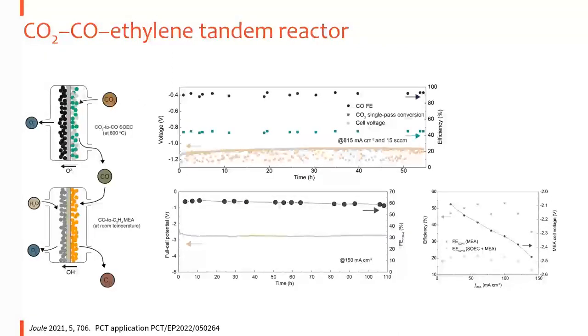So how can we do that? We are working on two different strategies. One is that we can separate the CO2 to ethylene conversion into two steps, which are CO2 to CO and CO to ethylene, and we can make a tandem reactor. In the first step, CO2 to CO, we can use a high temperature solid oxide electrolysis device, which does not involve protons and water, so that we do not have the OH ion generation problem, and CO2 will not have the chance to react with OH to form carbonate. Using this strategy, we can generate CO in a very energy efficient way. And using the CO to feed the normal MEA device, we can drive the CO to ethylene reaction.